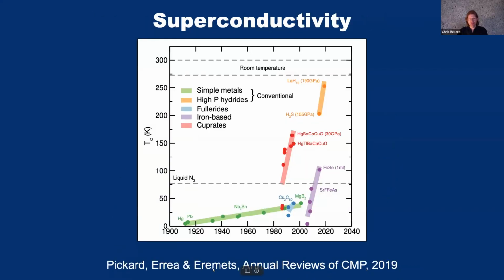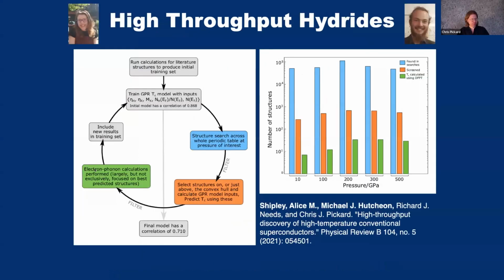Here's a review article I wrote with Mikhail Eremets, a very well-known experimentalist in this field, who actually discovered two of the structures that had been predicted by, not always myself, but other people doing structure prediction of high temperature superconductors under pressure. There's the lanthanum H10 compound and the H3S compound, which have exceeded the cuprate superconductors, albeit at very high pressures. Although we note that the record cuprate superconductor was only achieved at 30 gigapascals anyway. So high pressure had been exploited before to get these record superconducting temperatures. So we've been doing work on this again, following these early successes of predictions, again on a stoichiometry by stoichiometry basis.